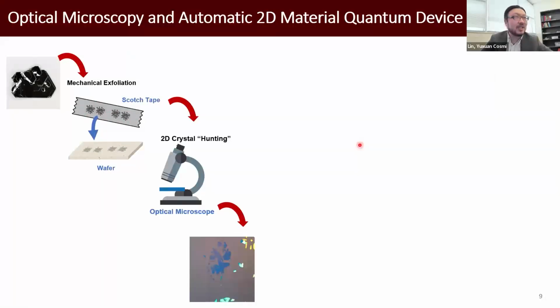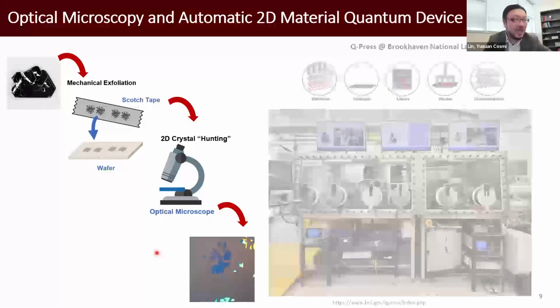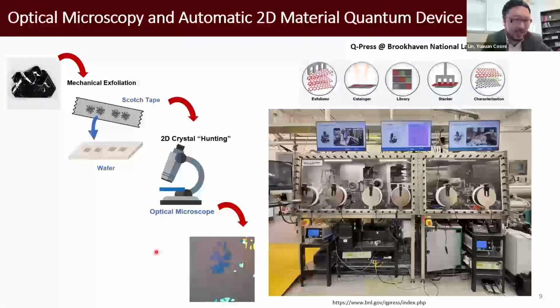Just a very simple example. Whenever you are working on 2D materials, especially devices, especially in earlier days, you have to use mechanical exfoliation and try to exfoliate those randomly distributed flakes on top of a silicon wafer. And then you need to sit in front of an optical microscope for hours trying to identify the good flake with a large enough area, good shape, and the targeted thickness, so you can stack them on top of each other and make heterostructures and devices.